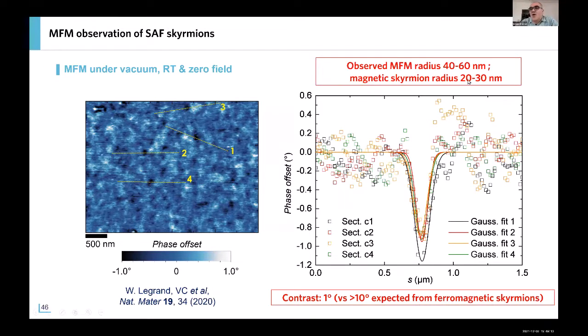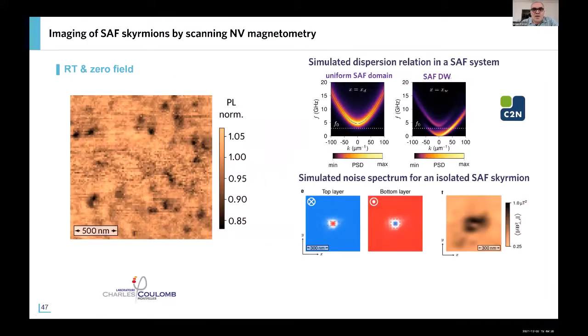And the radius we find is around 50 nanometers. But if we take into account the interaction with the tip, then we deduce that the real radius is probably closer to 20 or 30 nanometers. This was done by MFM under vacuum, but there have also been some studies by scanning NV microscopy by Finco and Vincent Jacques from Montpellier, and they find exactly the same type of structures, imaged in a new mode for scanning NV magnetometry called spin relaxometry.